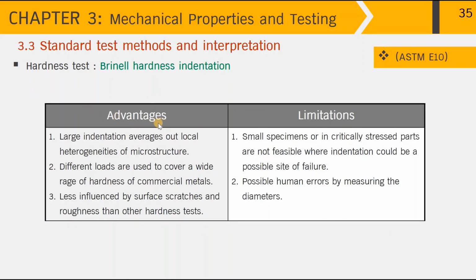Here I would like to summarize the advantages and limitations of Brinell hardness indentation. First, let's look at its advantages. The indentation is large so that it can average out local heterogeneities of the microstructure, meaning we can sample the test data over a large area. Second, different loads are used to cover a wide range of hardness of commercial metals, from softer materials like aluminum up to iron and steel, which is much harder. Third, it is less influenced by surface scratches and roughness than other hardness tests, because of the relatively larger indenter, a steel ball of 10 mm diameter, so the test results are less sensitive to surface scratches.